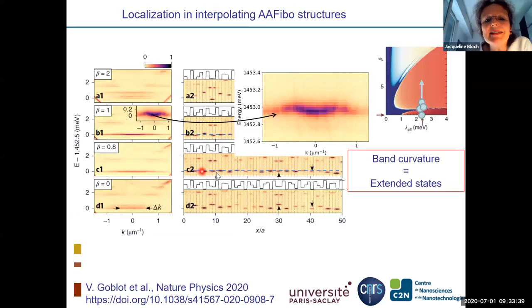Yes, so you see there is still some disorder. We can look along the wires to see a region where there seems to be a bit less disorder. If you zoom on this part, you would see that in the simulation, we expect something very flat and then there is some fluctuation. If you look at our paper in the supplemental, we provide the simulation of exactly the same kind of potential and the simulated pattern that we should see. So it's not bad. There is some disorder, but we still see very well.